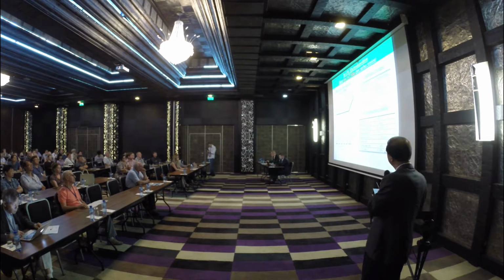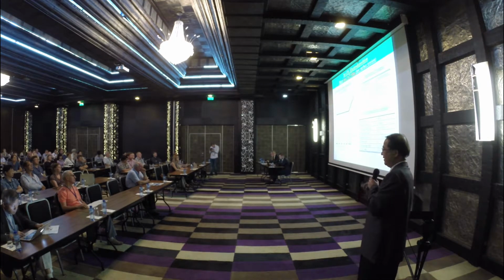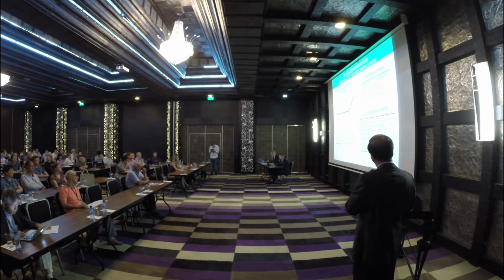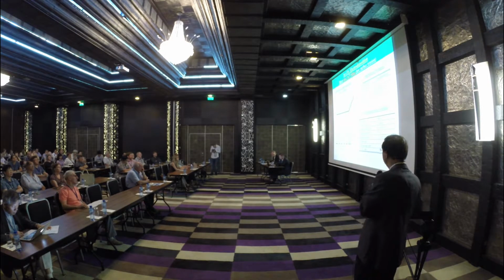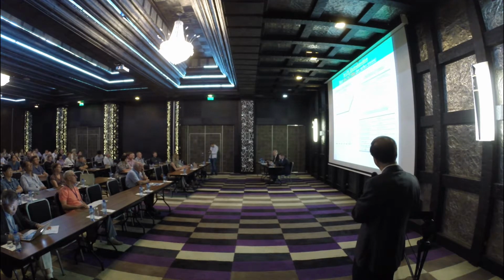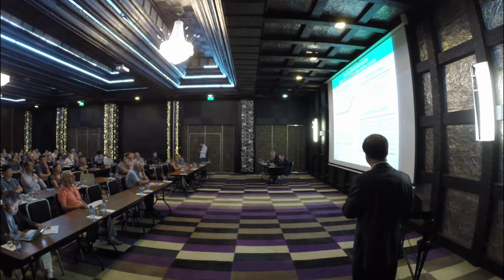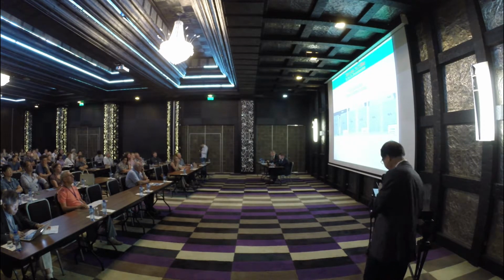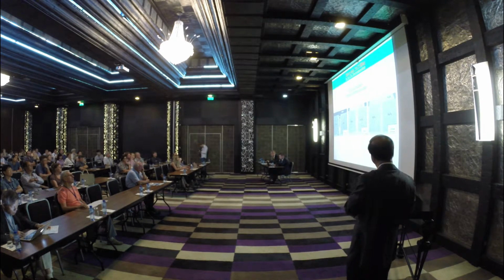In the first study, we used the sintered aluminum oxide as the substrate, and the micro hole array was prepared using a laser drilling. And the characteristic dimension of this cathode or this electrode is shown in this figure. The hole average size is about 50 micron, and the aspect ratio was 8 in this case. And we employ the electrodeposition using the conventional process and the supercritical carbon dioxide process, as we can see from this figure.